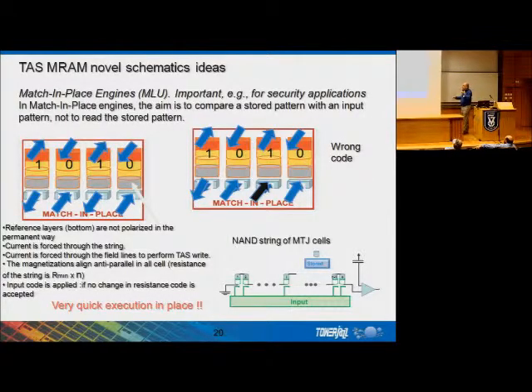And this is the last message that I wanted to show you, a new schematic idea which can be realized with magnetic memory and cannot be realized with resistive RAMs of other types. In this case, you make magnetic stacks which do not have reference layers. Usually, a magnetic stack has a reference layer and a storage layer. You store information in the storage layer while the reference layer is fixed. Here, I don't have reference layers. I make reference layers by forcing currents through special metal lines. At the same time, information can be stored in the storage layers, which are shown on the top of the memory cells.